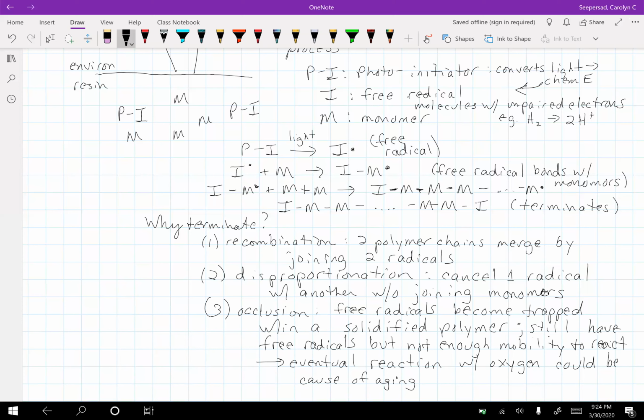So a lot of times these stereolithography parts, the materials do not age well. They yellow with time, they become more brittle with time. Some people, for example, have talked about placing stereolithography parts in a window where sunlight comes in, and over time they become so brittle that you just pick them up and they almost disintegrate in your hand. And so that's one of the real downsides of stereolithography, these photosensitive resins, is the fact that they sometimes don't age well, right? And so that's a downside.